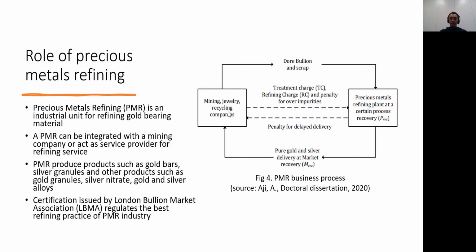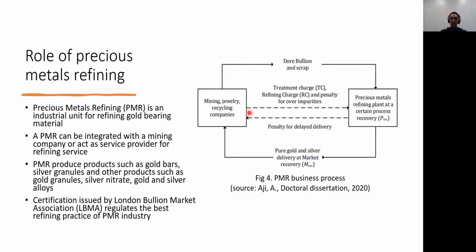In this schematic PMR business process, these two processes, mining and then precious metal refining, you can see there is this, sorry, I will put my pointer on. So you can see this straight line as the material flow, and this dash line as the accounting flow or the cash flow. So mining companies can send doré bullion and also some scraps containing gold to a precious metal refinery, and then they refine it, and then they send back the pure gold and silver at an agreed recovery.